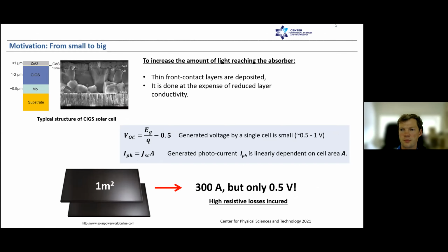To increase the amount of light reaching the absorber, you have to make these contacts thin, but this is done at the expense of reduced layer conductivity. If you want a thin film module of 1 square meter, you are limited by the voltage of a single cell, from 0.5 up to 1 volt. That means you can end up with a very high generated current and really high resistive energy losses, and it's not optimal for the device.